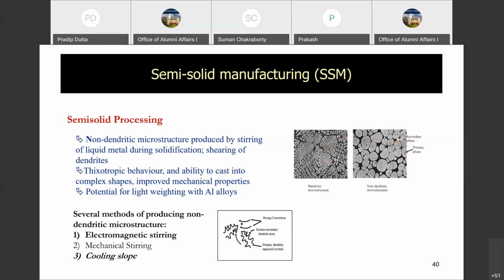Now, what happens to this kind of microstructure, as we see here, is it has a thixotropic behavior. If you heat this and melt the eutectic, then these particles, the primary phase, will not be molten because it has a higher melting point. So at that kind of state, it would have a thixotropic behavior, which means that it is shear thinning. And then it has the ability to be cast into complex shapes with improved mechanical properties, because you will not have solidification shrinkage, and so on.